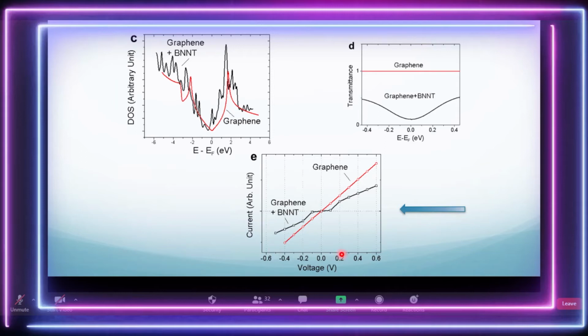This is a very nice result in a sense. Although it's a very simplified model, it tells the current versus voltage. This is our zero, this is a positive bias, and this is a negative bias. Graphene in red behaves like graphene, a zero gap material, with very, very high current as you apply either positive or negative bias. But if you bring in this BNNT, what happens at the interface? We see some sort of a plateau here, which reflects the intrinsic property of BNNT, because BNNT is semiconducting. And then, of course, current rises because of the presence of graphene.